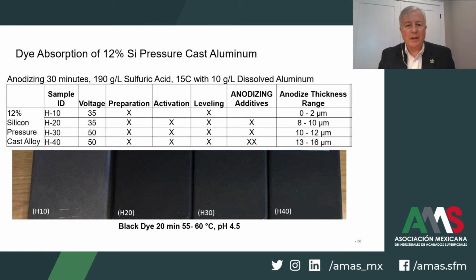As shown with the data for a 12% silicon pressure cast alloy with stage 1 and stage 2 processing, we can demonstrate the improved oxide thickness and improved pore structure does have a very positive effect on the impact of the dye color as shown here in the following photomicrographs. We limit the leaching of the color during the post-rinsing. The processing of the anodized cast alloy compared to the different options in the cast alloy process can be shown in this different slide.